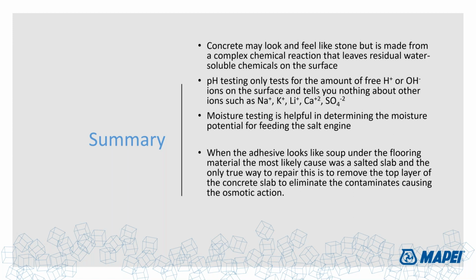pH testing, although it's good, is only going to test the amount of free hydrogen ions or free hydroxyl ions, which is indicative of how early the concrete is, how much calcium hydroxide is on the surface, and so on. But it doesn't tell you anything about that other chemical soup, which we already know is in there based on what's going into the concrete mix to begin with.